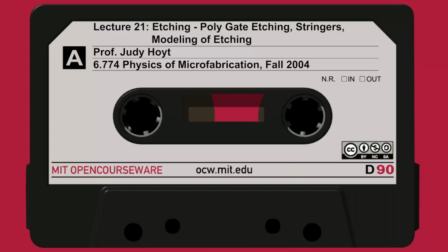Silicon nitride: there are some isotropic etches like CF4 and O2. An anisotropic etch is CF4 and H2. This one is selective over silicon, so it'll stop on silicon, but not over SiO2. And sometimes you have stacks consisting of oxide and nitride, and you need to etch one of the two selectively. So it gets a little tricky. You need to pick the etchant and the reactor carefully.